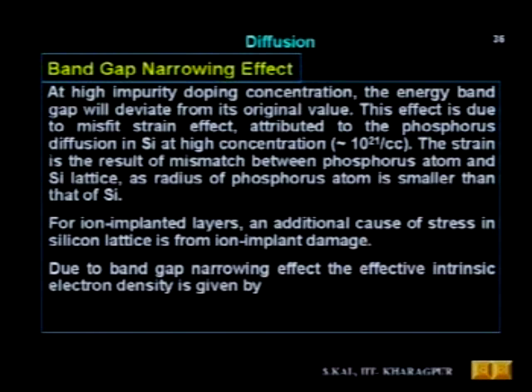Now, another high concentration effect is the band gap narrowing effect. What is that? Band gap narrowing effect is that if you increase the dopant atoms excessively, in the range of 10 to the power 21 per cc, then the band gap of the silicon will not remain constant. It will change. It has been observed that at high impurity doping concentration, the energy band gap will deviate from its original value. This effect is due to the misfit strain effect attributed to phosphorus diffusion in silicon at high concentration, 10 to the power 21 per cc.